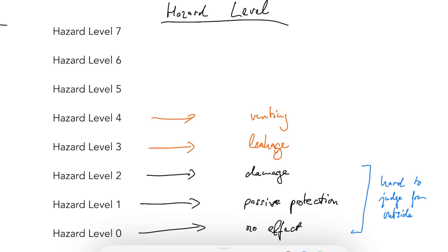One, it's very hard to really measure. I mean, you can measure how much weight loss there is after the test, like how much the cell weighed before, how much it weighed afterwards, and then you have the difference. What is very difficult to assess is how much electrolyte was there. There you need to trust the numbers from the manufacturer. Either you are the manufacturer and you know it exactly, or you get a paper and it says there's so much electrolyte inside, and then you have to trust it.